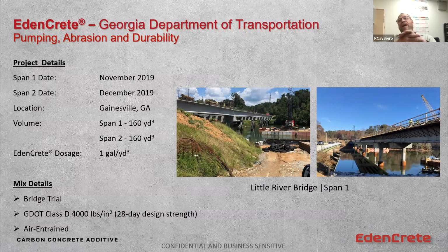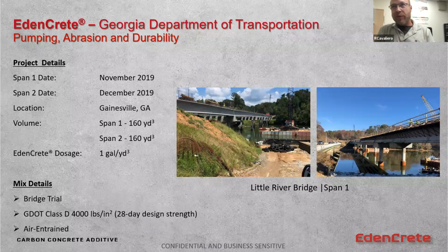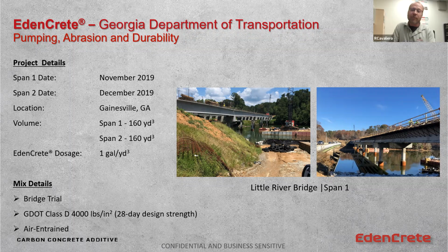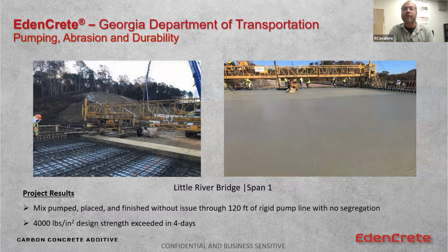We also move into bridge decks, right? Bridge deck applications are plagued with challenges, right? You've got suspended slabs. They experience a lot of frequency, a lot of bending. Cracking is inherently a problem. So we went down and we learned of the delays in their construction schedule, why they wait for the concrete to obtain strength. So we went down and we did a trial, and they put EdenCrete in the first 2 spans, and we actually achieved the design compressive strength in 4 days. Their mixes were typically achieving it in about 22 days.